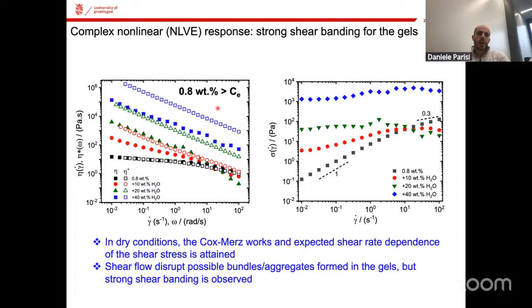So this is just to give an idea. Rheologically we can have two types of viscosity. One viscosity that we call eta star here is the viscosity that we detect when almost no deformation is provided to the material. Then we have this other viscosity with no star, which is the viscosity that we attain during steady shear deformation of the material. It's like I have my rheometer, the sample is sandwiched between two plates, and one plate rotates continuously. When the viscosity under this strong flow is much lower than the one that you measure at small deformation, it means that the strong flow you are providing is disrupting the network significantly.